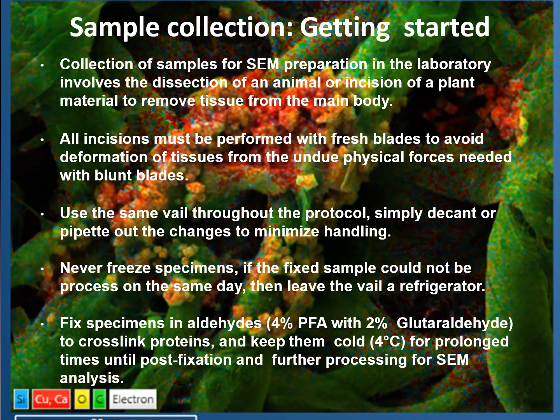Sample collection, getting started. Collection of samples for SEM preparation in a laboratory involves the dissection of an animal or incision of plant material to remove tissue from the main body. All incisions must be performed with fresh blades to avoid deformation of tissues from the undue physical force needed with a blunt blade. Use the same vial throughout the protocol. Simply decant or pipette out the changes to minimize handling. Never freeze the specimen. Fix specimens in aldehydes, for example 4% formaldehyde and 2% glutaraldehyde, to cross-link proteins, and keep them cold at 4 degrees for prolonged times until post-fixation and further processing for SEM analysis can happen.